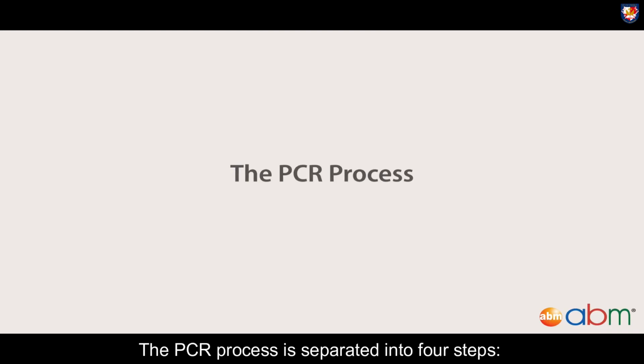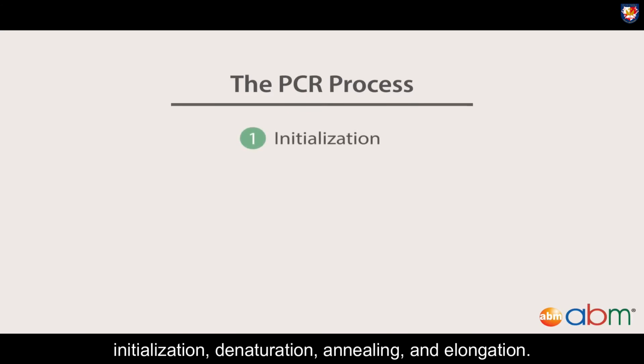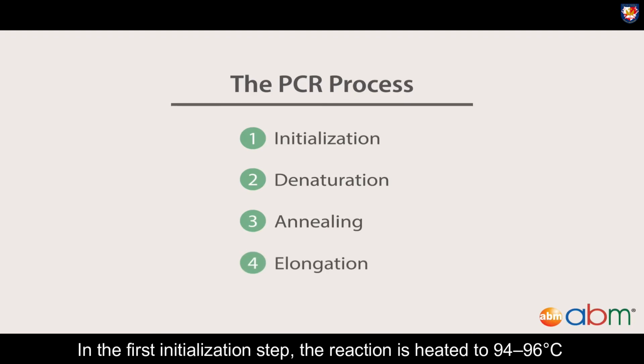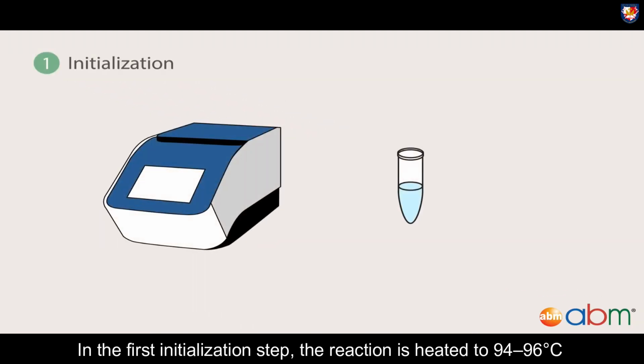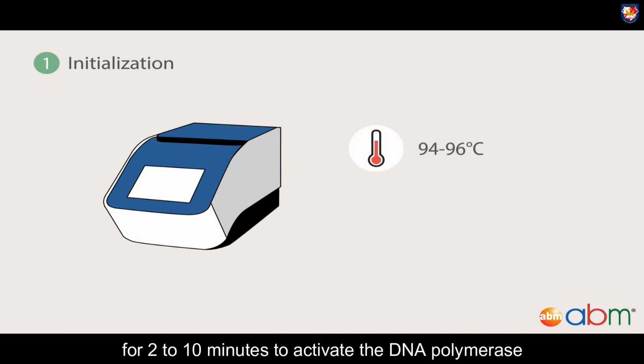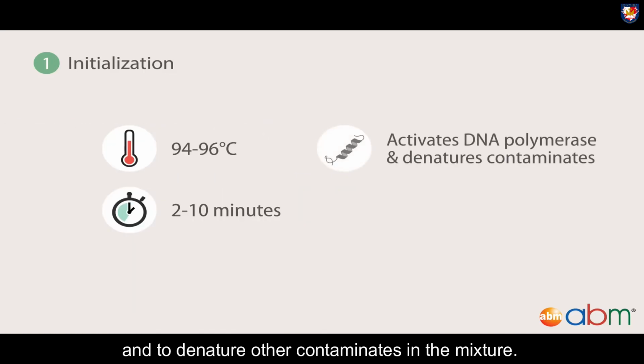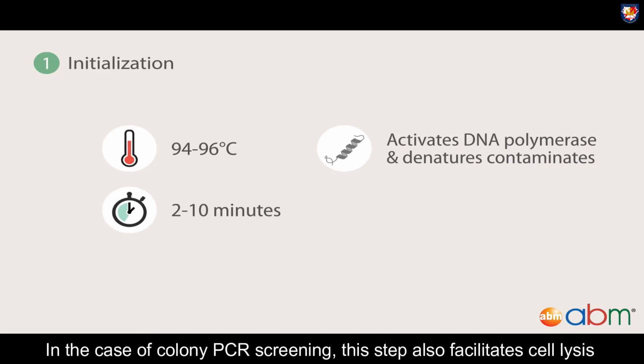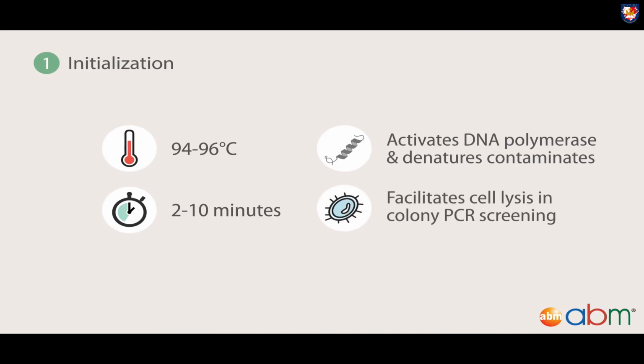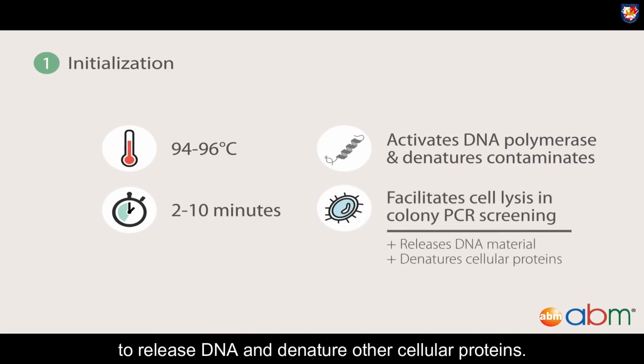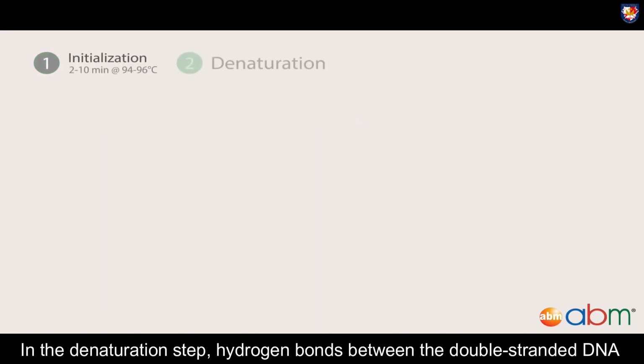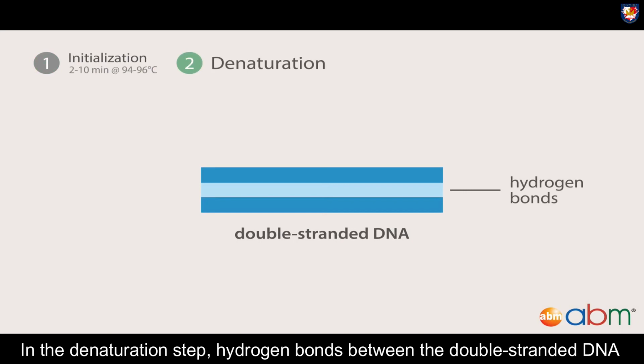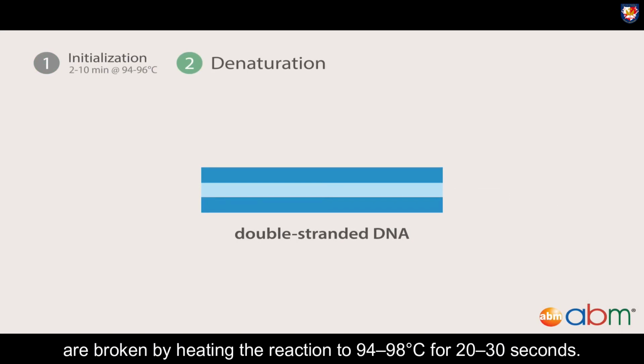The PCR process is separated into 4 steps: initialization, denaturation, annealing, and elongation. In the first initialization step, the reaction is heated to 94 to 96 degrees Celsius for 2 to 10 minutes to activate the DNA polymerase and to denature other contaminants in the mixture. In the case of colony PCR screening, this step also facilitates the cell lysis to release DNA and denature other cellular proteins.